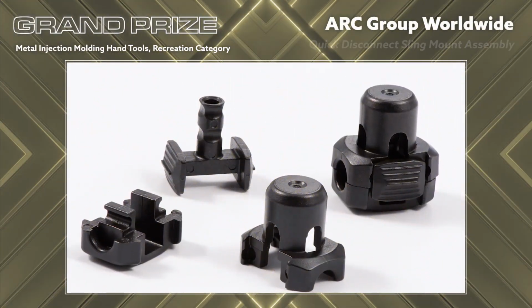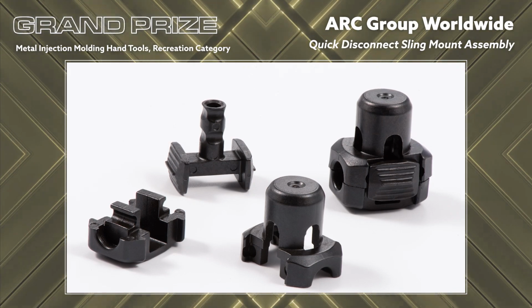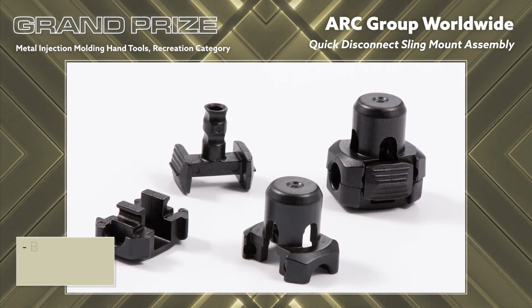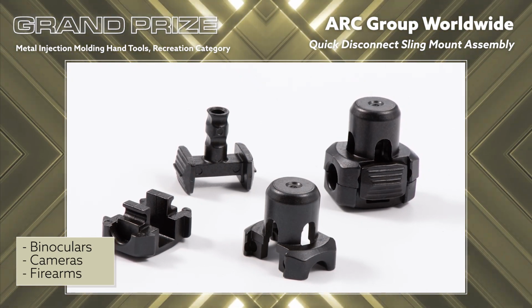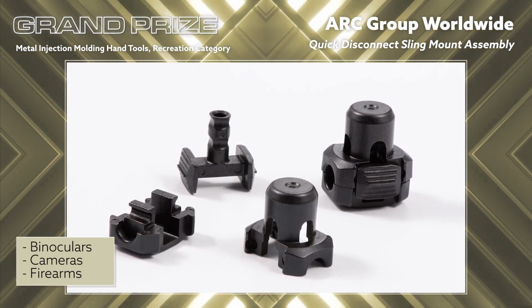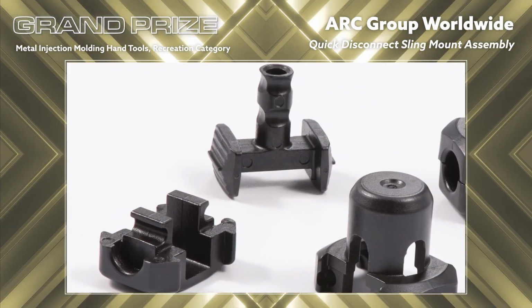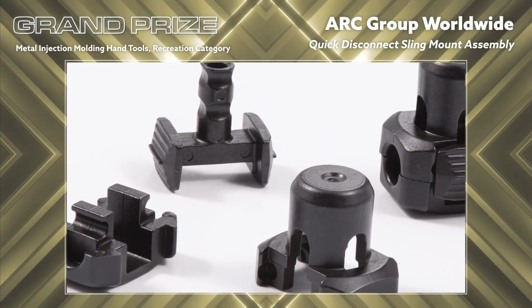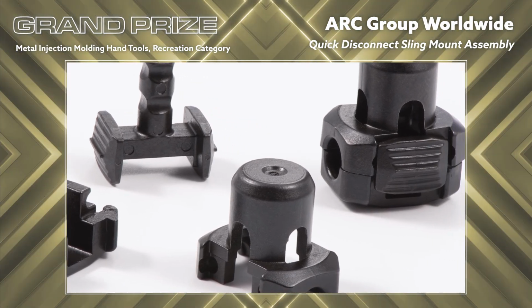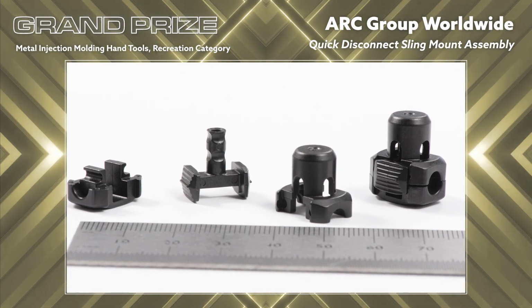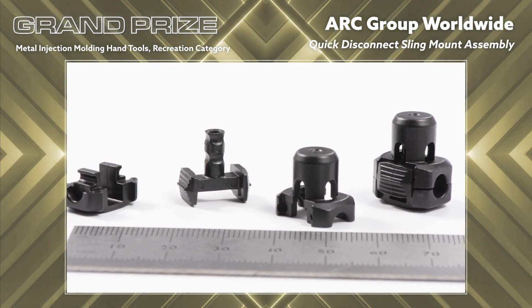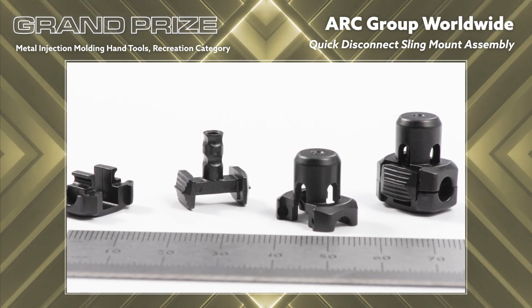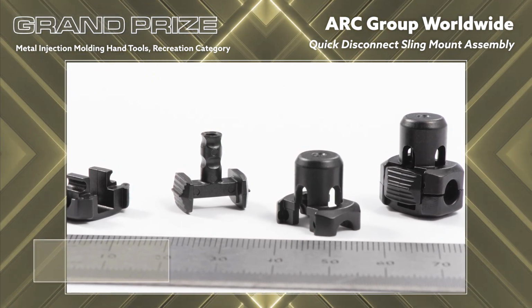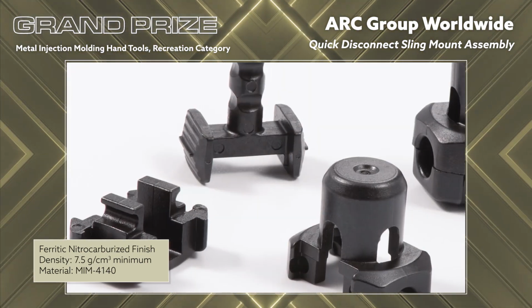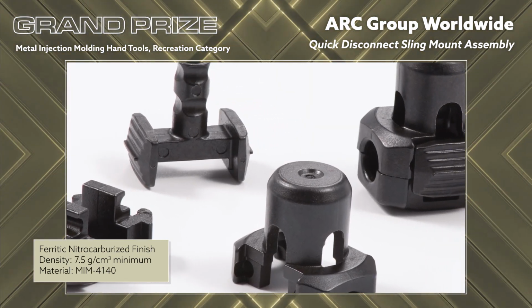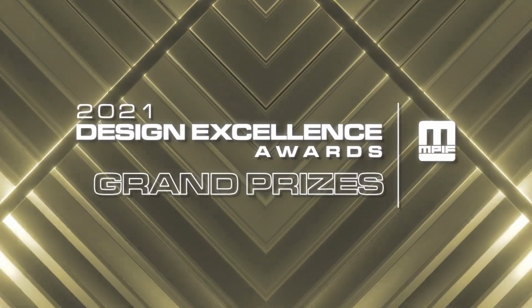In the hand tools recreation category from MIM components, a grand prize has been awarded to ARC Group Worldwide for a quick disconnect sling mount assembly used for a variety of small handheld devices like binoculars, cameras, and firearms. Detailed design discussions with the customer allowed for a near-net shape molded assembly. Utilizing MIM enabled the incorporation of smooth transitions and rounded edges, as well as the elimination of any machining marks on the visible portions of the parts. 2 of the parts are sintered to near-net shape and sized. The 3rd part requires no sizing step. All 3 are heat treated and given a ferritic nitrocarburized finish. The parts are made to a 7.5 grams per cubic centimeter minimum density using MIM 4140.